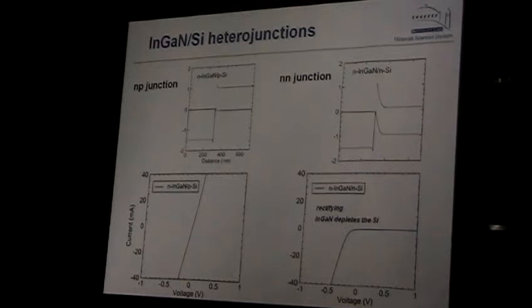So we made junctions like that, first to test if our assumption was correct. So we grew n-type indium gallium nitride on p-type silicon. Normally when people grow p on n or n on p, you should have a rectifying junction. But we knew that it should be perfectly ohmic, and it was. So it was a really good tunnel junction. However, counterintuitively, when you grow n-type indium gallium nitride on n-type silicon, there's no change in type of conductivity. We have rectifying properties, and this shows the rectifying properties. This is the I-V characteristic, current versus voltage. We found this junction at the interface because of this unusual alignment.